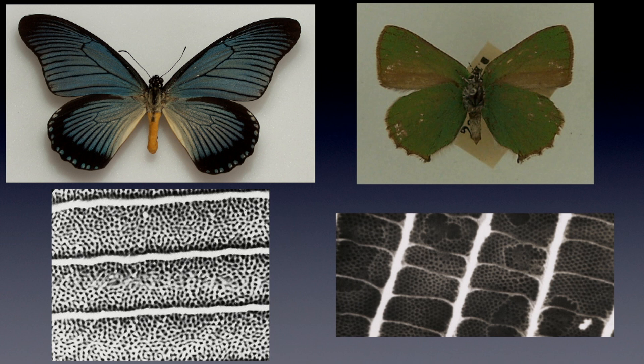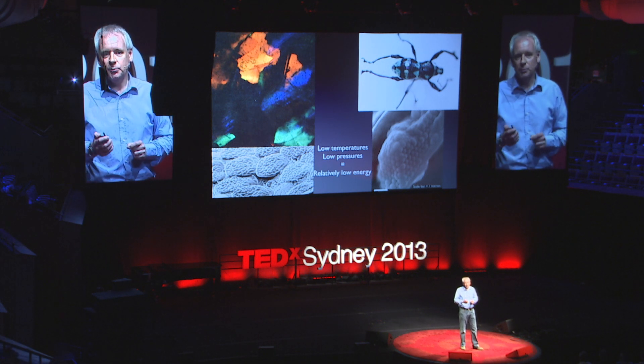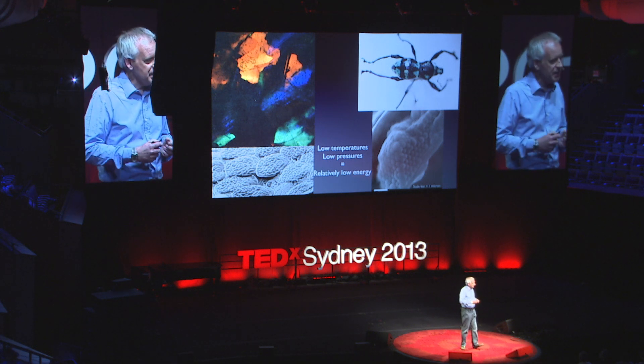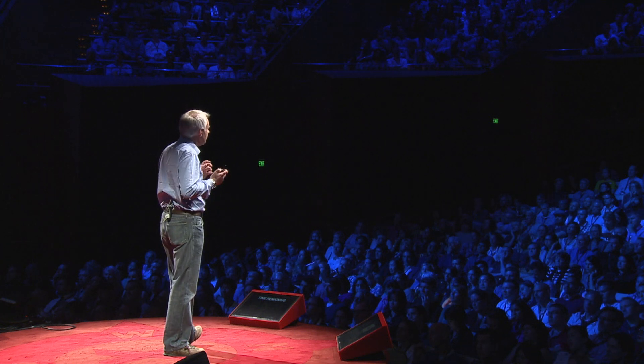Now a good example of a photonic crystal is opal — the gemstone opal, as you can see in this top-left picture. Opal is filled with tiny nanospheres that are close-packed together, and light rays come in and bounce around inside this structure and interact with each other to produce these iridescent colours. Interestingly, I found opal in 2005 in a weevil — a living animal producing opal. Opal has lots of technological applications, such as in computer chips, but industry makes it at high energy costs, requiring high temperatures and pressures. However, animals are doing this at room temperatures and pressures, magically mixing together chemicals to produce perfect opal at very low energy. So we're trying to image these scales in living weevils to work out how they're making these devices, and see if we can bring this process to industry.